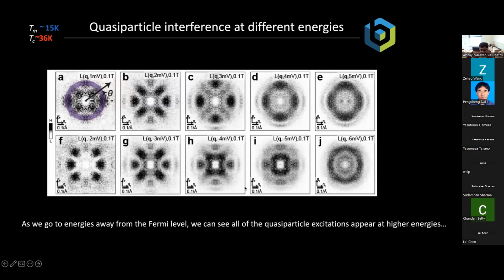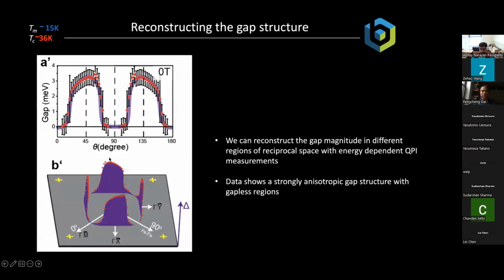And finally, let me just finish by saying we can look at the energy dependence of these patterns. So we can go to higher energies above the Fermi level. And as we go to higher energies above the Fermi level, we can see all of the quasiparticle excitations appear at higher energies. So here, for example, at 5 millivolts above the Fermi level, you can see a full circle appear, and that's the full Fermi surface, where now there's quasiparticle excitations all across the Fermi surface. And using data like this, we can actually reconstruct what the superconducting gap function looks like in reciprocal space. And what we see is that indeed there are regions of reciprocal space where there are gapless regions of this Fermi surface, verifying that this indeed is this kind of Bogoliubov Fermi surface that was predicted from theory.